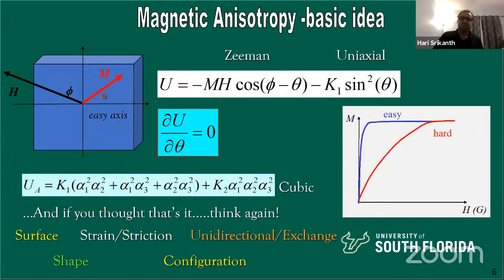So to understand magnetic anisotropy, let's apply a magnetic field on a magnetic material, and that's the internal magnetization. Of course, to understand magnetism, you have to go all the way to quantum mechanics because magnetism is rooted in quantum mechanics. We can't do that. We don't have that time. So let's start with the effective magnetization of this material, which is that one right there. So when you apply a magnetic field, this magnetization vector is now feeling two different energies, okay? So one is the internal magnetic energy, which is determined by the magnetic anisotropy. That's one of the primary contributions to the internal magnetic energy. And the other one is due to the external field.